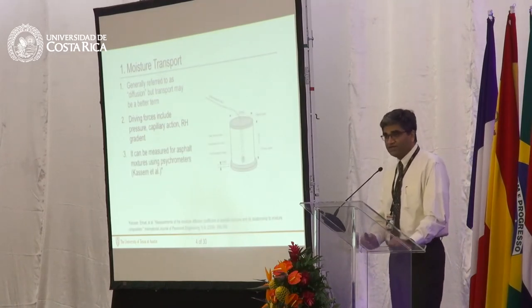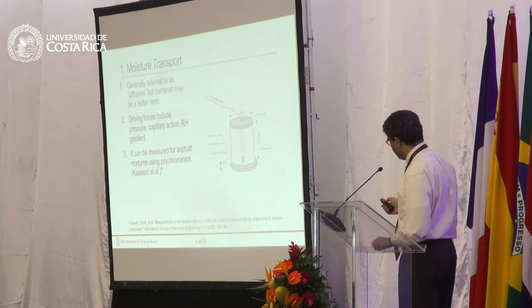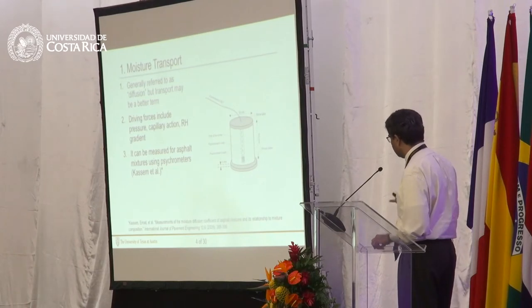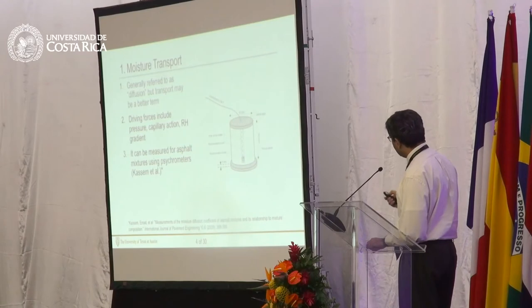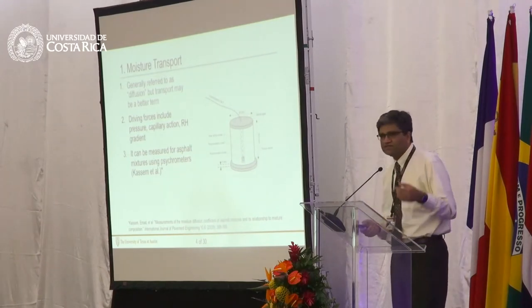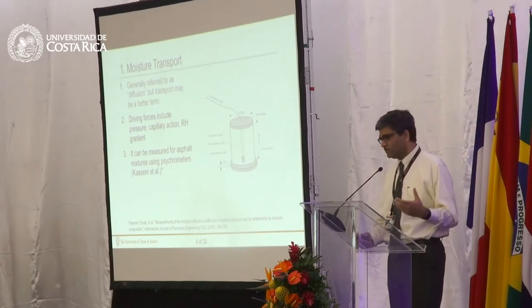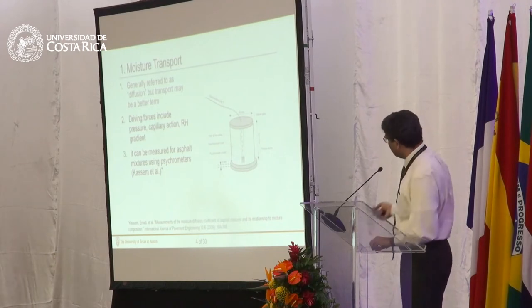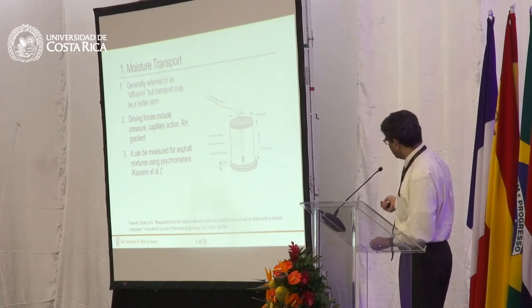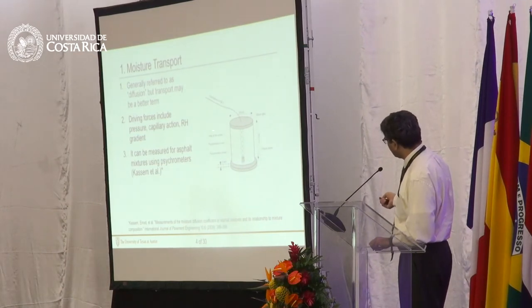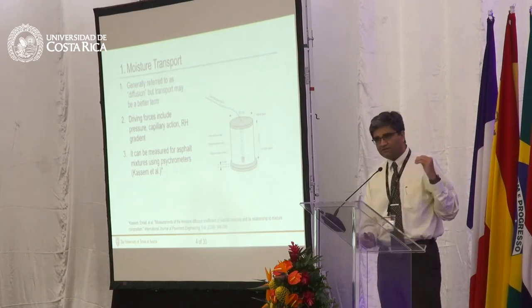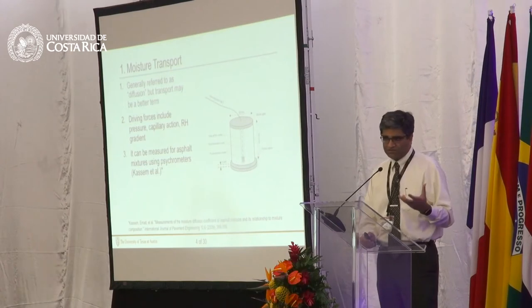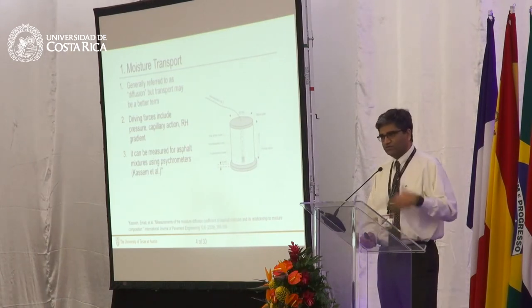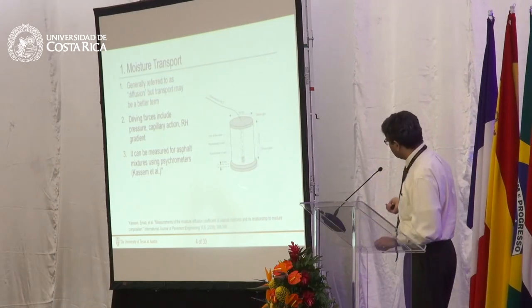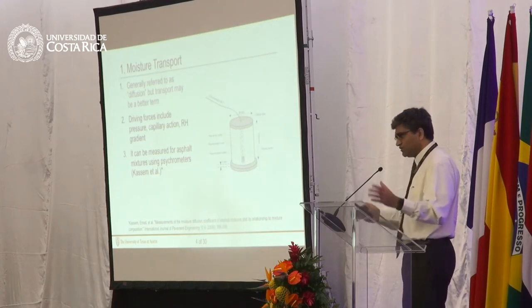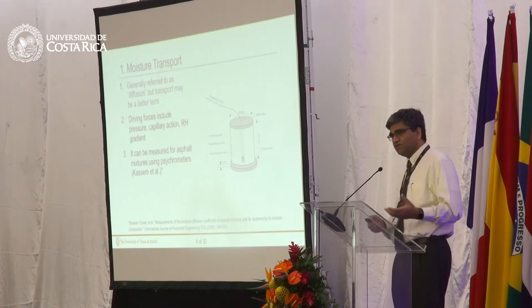Can we measure it? Can we examine it? Yes. This is one study that I cite here by Emad Kassem, who was at Texas A&M University at the time I was there as well. He's right now a faculty member in Idaho. He used a technique with a psychrometer, which is basically a sensor that measures moisture. You can embed this psychrometer in an asphalt mixture specimen and change the boundary conditions. You can leave one boundary dry and the other soaked in water, and you can implant two or three or four of these sensors along the height of the specimen and track how much moisture is building up. You can apply things like Fick's law and back calculate for diffusion or transport, or use any other suitable model that tells you the rate at which moisture goes from one end to the other, given a certain boundary condition. It can be done, it's been measured, documented, and these numbers are there in the literature.